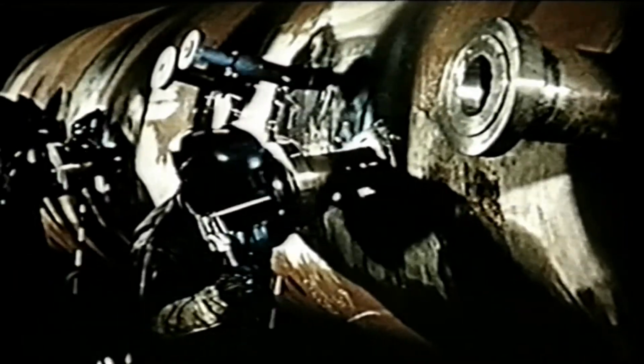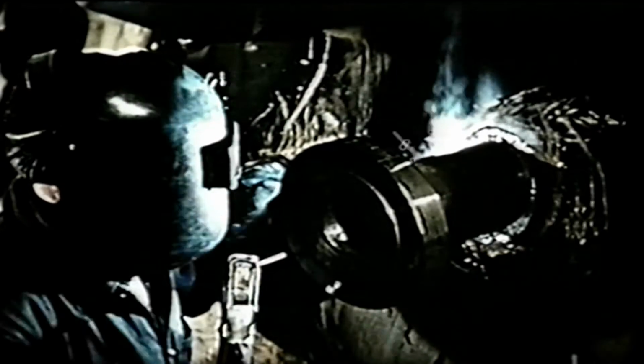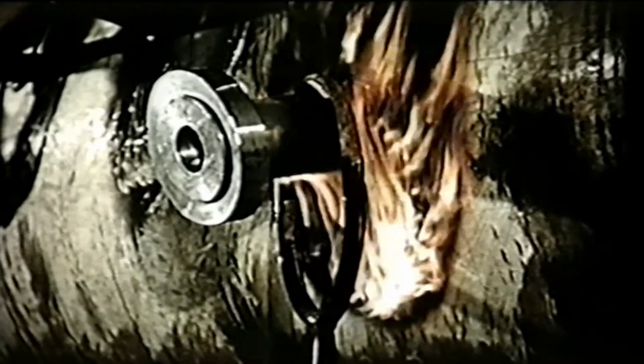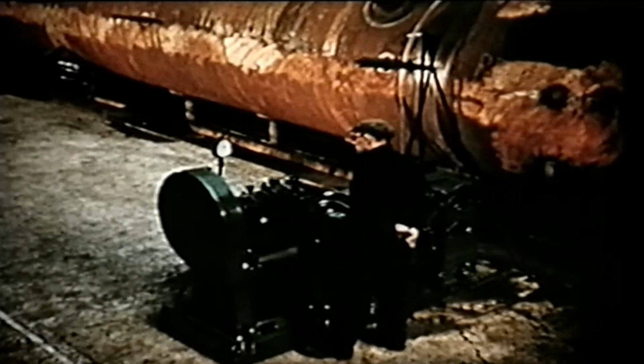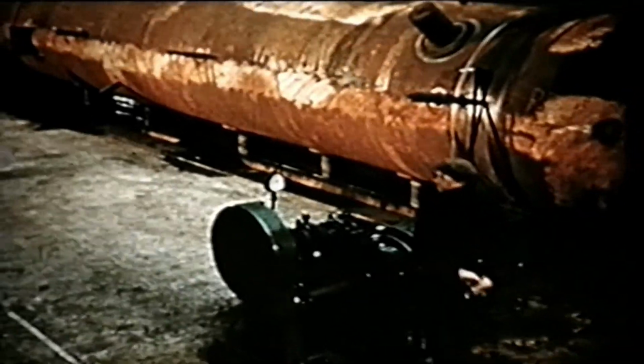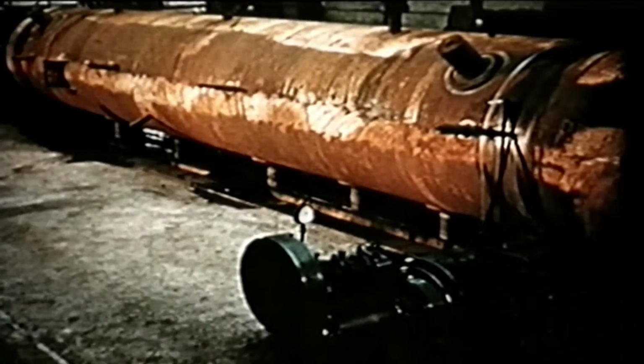Local stress relieving is carried out after the welding of each fitment. When all welding is completed, the entire drum is stress relieved in a furnace. With manhole covers fitted and holes in the nozzles temporarily plugged, the drum is ready to be tested under hydraulic pressure. The test pressure is almost 50% higher than that encountered under working conditions.